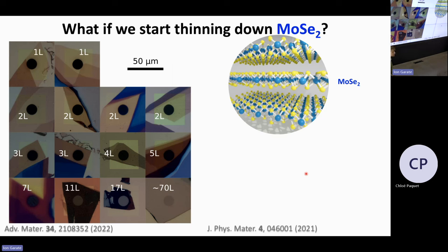And we made a lot of devices. And with we, I mean my students in the lab. What I think is very nice of them is that they also made multiple samples of the same thickness, because you can get a lot of sample-to-sample variation, which you don't often see in the literature in the 2D field. By doing this, for example, you have four bilayer samples. That gives you an idea of how much variation there is just from sample to sample, even though the thickness is the same.